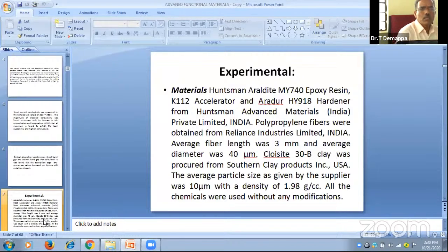Research method or experimental method. What are the materials we used? Especially the first one, the polymer composite we are talking about. For polymer composite, FRP composite, fiber reinforced plastic, the first FRP was used by Dr. APJ Abdul Kalam for aeronautic applications. Here, the matrix is epoxy resin of grade MY740, the accelerator, that is the curing material, is K112, and the hardener is HY918. Depending upon the epoxy grade, a suitable hardener is also very important, and the selection of this combination is very important. These materials were procured from Huntsman Advanced Materials Private Limited, India.